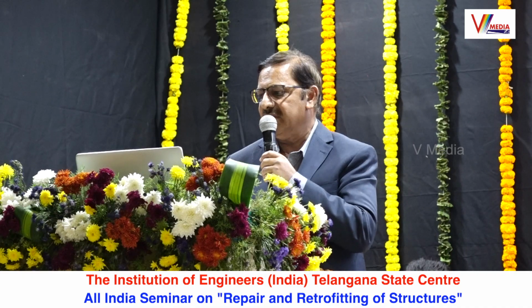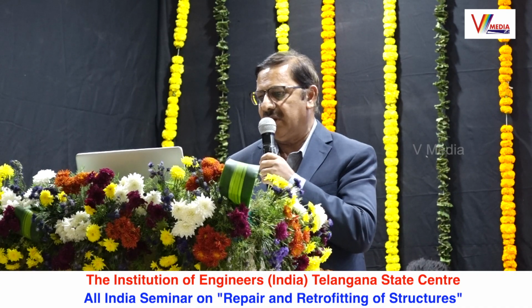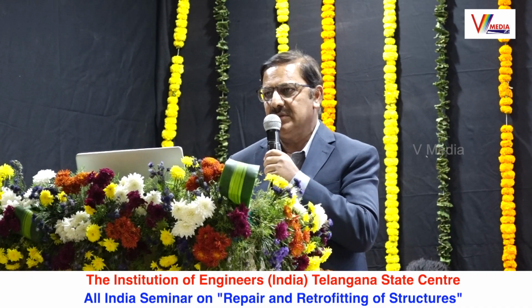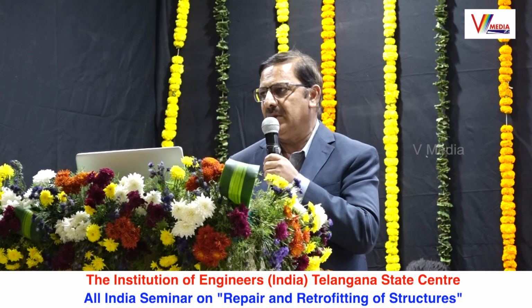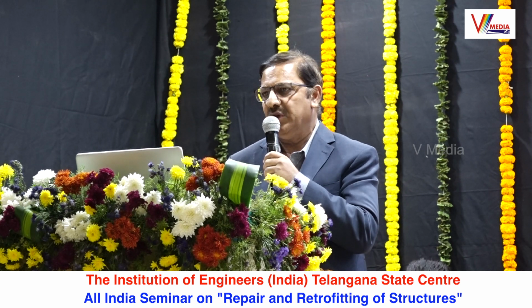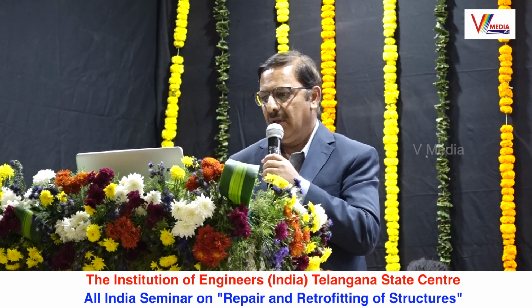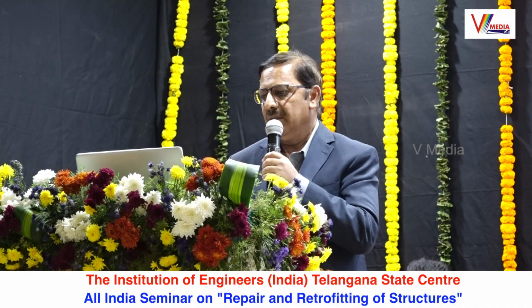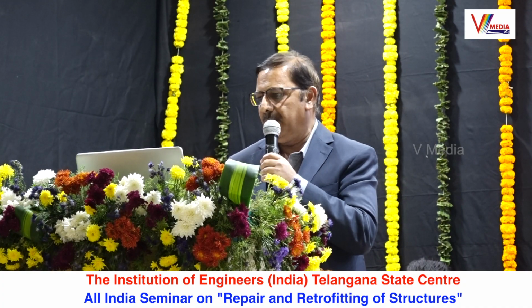When the alkalinity breaks down, because chlorides are present from the beginning or carbon dioxide enters from the environment into the concrete, corrosion propagates, and the corrosion products build up, causing cracking.